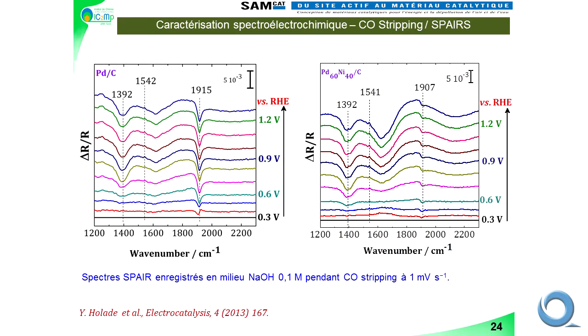Maybe with a nanobalance combined with some techniques. But when we combine with spectroscopy, for example, we have some idea. As you can see here, at 0.4, we have oxidation of CO to CO2. We have some evidence, but it's not enough. This means that at 0.4, we have to prove that we have oxygen at the surface. We cannot have this evidence. And with a co-catalyst, with nickel, we have at the same time a much earlier CO oxidation to CO2.